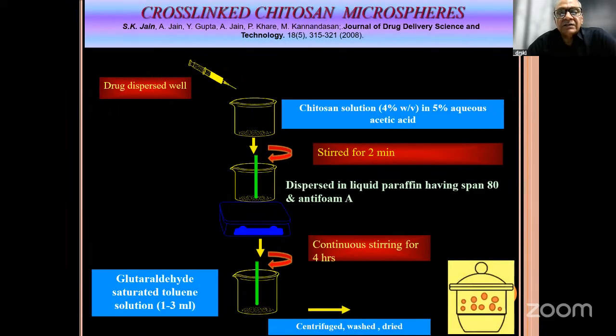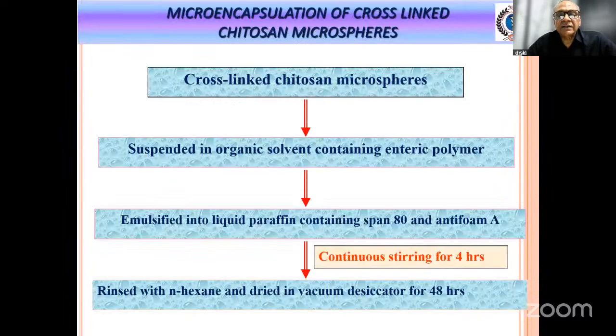This is about the cross-linked chitosan microspheres. We use the dispersion method for preparing the chitosan microspheres, and rigidize them with a glutaraldehyde-saturated toluene solution. Since these microspheres are quite adhesive in nature, delivery through the oral route is difficult. They will adhere at the upper part of the GIT. So we coated them with an enteric coating polymer using the emulsification method. After coating, the microspheres were centrifuged, rinsed with n-hexane, and dried in a vacuum desiccator for 48 hours.